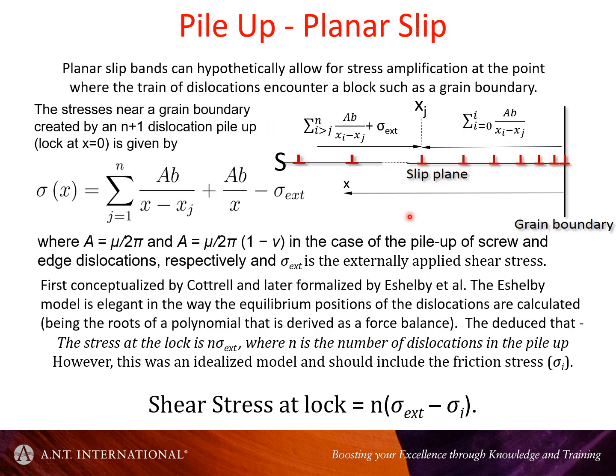I'm not going to go through this, but ultimately there have been lots of studies about it. But what you need to pay attention to is that by considering situations such as this, where you have dislocations which are emitted from a source, it could be screw or edge dislocations, and then these dislocations move along a slip plane and then come into a block, a barrier. The stress at this point, the shear stress in this particular case, can increase significantly, and the shear stress of the lock is given by this expression, where n is the number of dislocations in the slip band, and the external shear stress is given by sigma ext, and sigma I is the lattice friction stress.